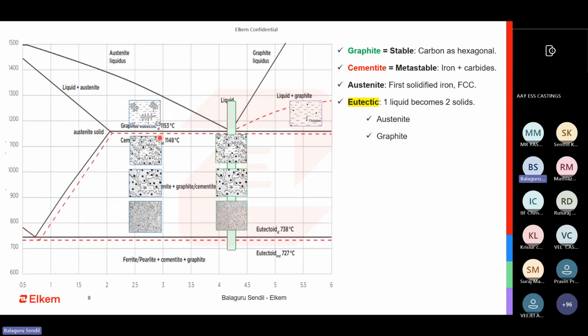In the case of the hypo composition, you first have your austenite growing, and then you see the black torch graphite growing, and then they join together, and the microstructure looks different. I will show a much better picture to visualize this. And when you are in the hyper region, you first have your graphite coming out, and then you have the austenite agglomeration around it, and then finally you have a microstructure like this. When the metal is cooling down from a normal pouring temperature of 1400 to room temperature, till about 700 degrees Celsius, you have this process happening.